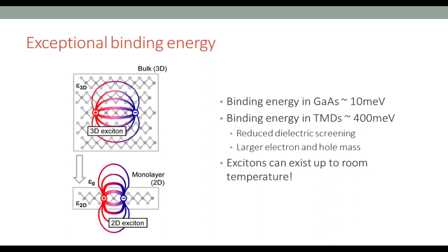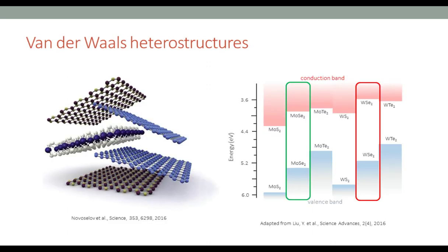In our case, for the TMDs, we have around 400 meV binding energy. So what this means is that we can do these measurements from room temperature down to low temperature, and in general, the energy scale and the temperature that we can explore these materials is at a higher energy. And this is due to the reduced dielectric screening when you reduce it to the two-dimensional limit. So I mentioned before we can stack these materials on top of each other, and that's what we do with these materials.